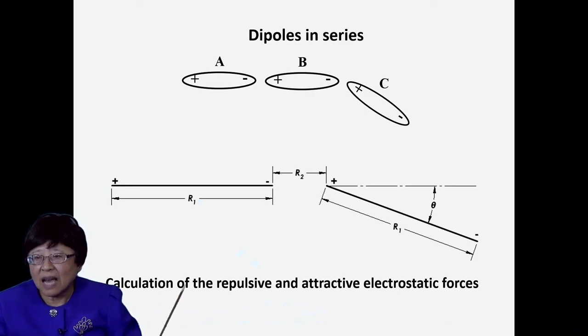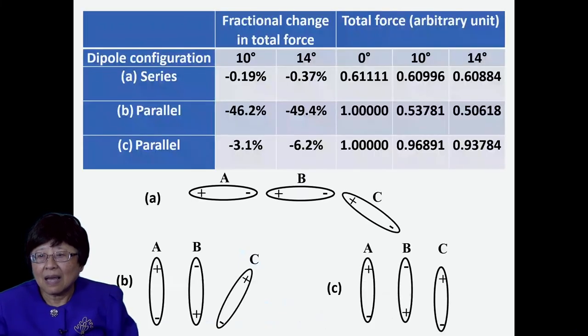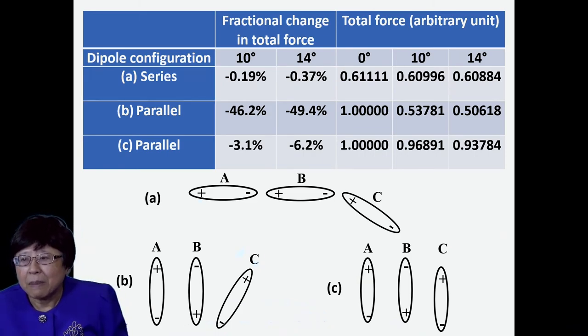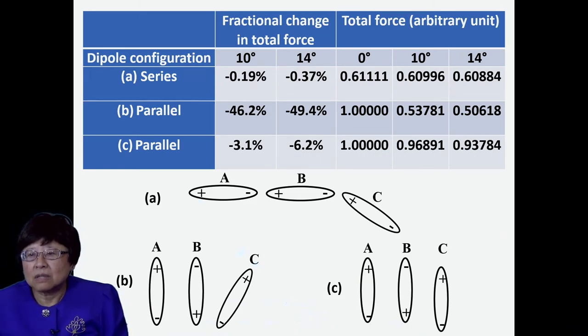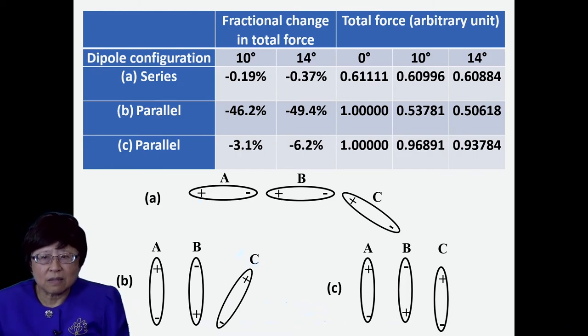And we've actually calculated the electrostatic forces involved between these plus and minuses, and found that indeed the bending diminishes the attractive force, so that it becomes less and less attractive between the dipoles. That is less and less dipole interaction.